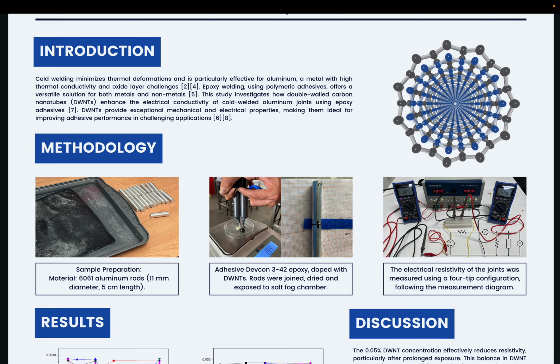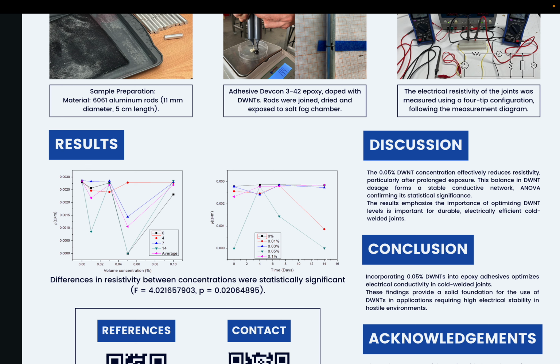Our results show that the incorporation of DWNTs into the epoxy adhesive significantly affects the electrical resistivity of the cold weld joints. Initially, at time 0, the resistivity varies slightly across samples with different concentrations. However, as the samples were exposed to the salt chamber over time, this difference became more pronounced. Notably, the 0.05% DWNT concentration was the most effective, showing the greatest reduction in resistivity over time.